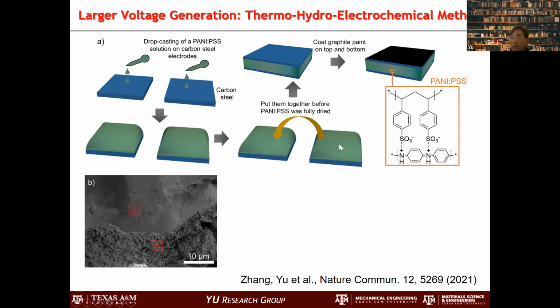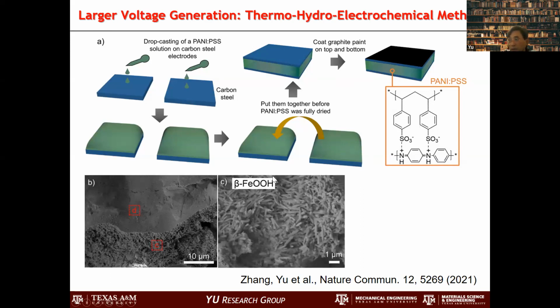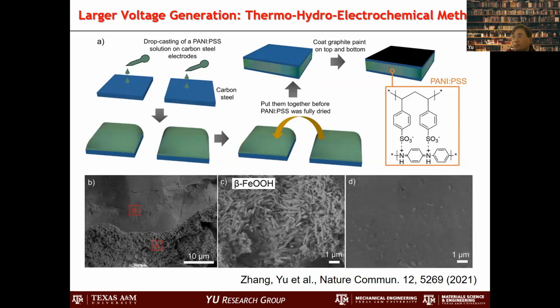What happens here is underneath this layer, it becomes very porous. Because of corrosion, we can create the beta phase FeOOH, a kind of nanostructure, and it becomes very porous. Then we can put a little bit of moisture here, and because of the moisture, the corrosion becomes a little bit different, depending on the moisture level. So we initiated the hydroelectrochemical method together with the thermal. That's what we have done. When we have different water contents on one electrode versus the other, we get a different corrosion potential and make a very, very large potential difference.